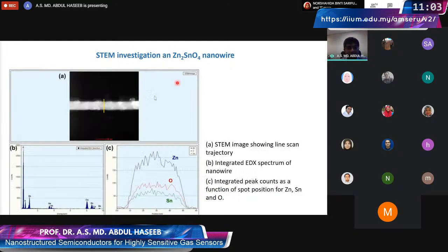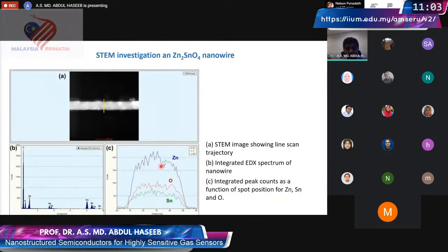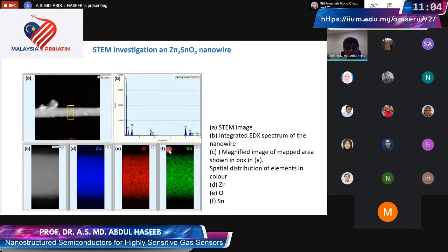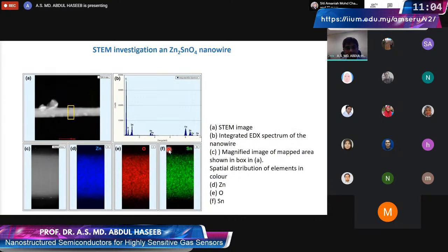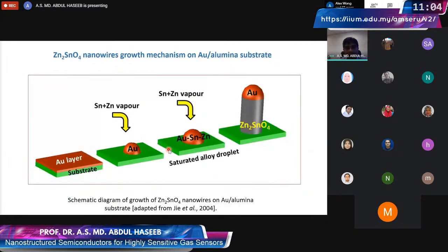And we confirm this again on STEM. We see the uniform mixture of tin and zinc without any shell formation. So on this substrate, we get a mixture of tin oxide and zinc oxide, which is further confirmed here in mapping. And this is the mechanism that we find in the literature, that indeed gold can catalyze this formation,